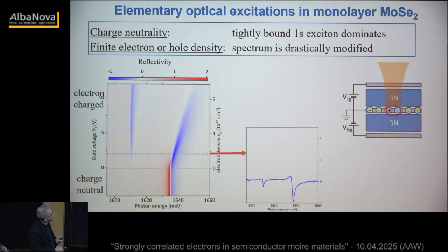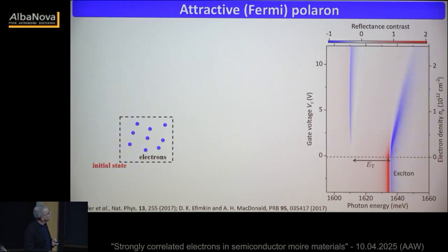What is really important is what happens when we inject carriers into the system. When the carriers are in, you see that two things happen. The excitonic resonance broadens and loses strength. And there's a new resonance appearing at a lower energy that is directly linked to the interaction between excitons and the free carriers. So how do we understand this? We start out now no longer in a neutral system. The initial state of our system is electrons in some state. In this case, this is supposed to describe a Fermi liquid, but it could also be a liquid crystal. So this is where we start.